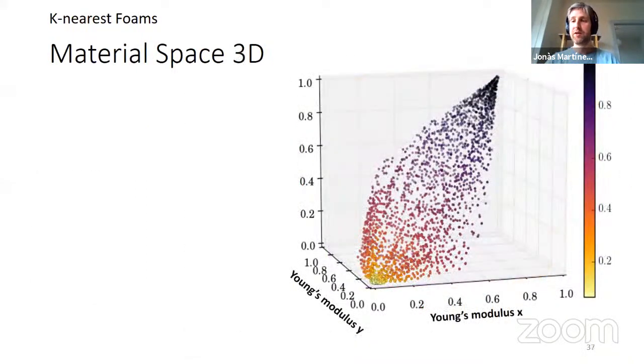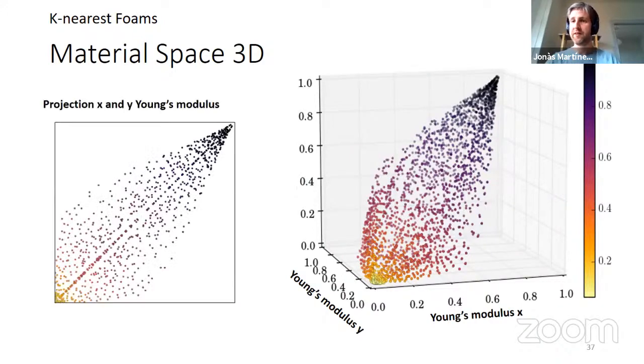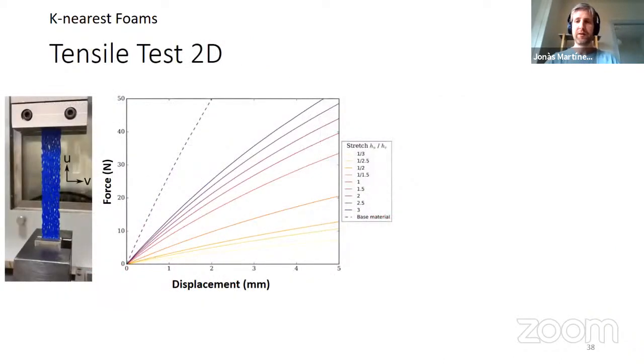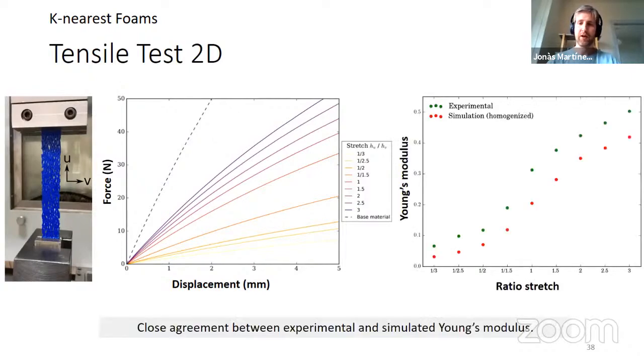And here you can see an image for 3D, which also expands a pretty nice space. We also did tensile testing to verify this, because let's not forget that all these simulations are done with linear elasticity, which assumes very small strains, so it's only valid for very small strains. We did some tensile tests, and we see a close agreement between the predicted and the experimental results, at least in terms of relative correlation.